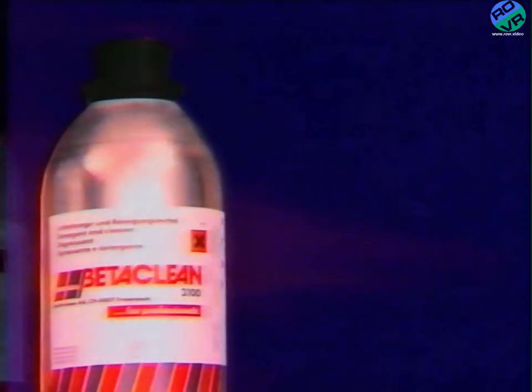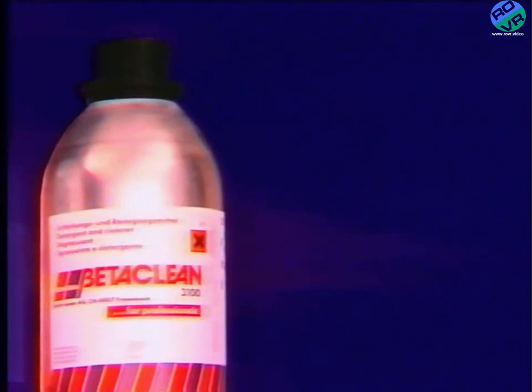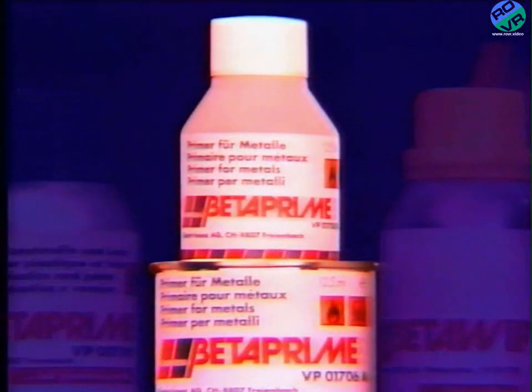BetaClean 2100 bare metal cleaner is a degreaser and cleaner for use on bare, uncorroded metal. The twin pack, BetaPrime VP 01706 A plus B, is an anti-corrosive primer for use on bare metal. Removal of any rust is essential before using BetaPrime VP 01706 A plus B to eliminate any possibility of the bond failing.